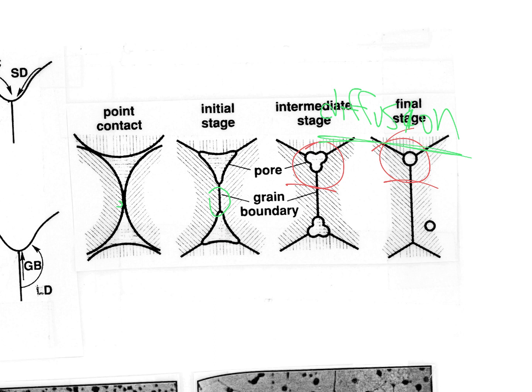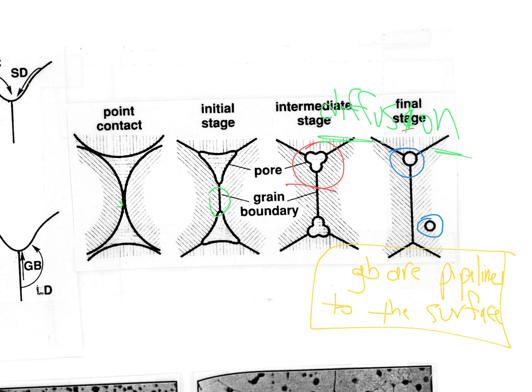All right, and a couple things can happen. Let me erase that part, and it shows you this here. We have pores in a couple of different places. This is a pore, and we've seen these before. It's on the inside of the grain. All right. And then we have a pore that's on the grain boundary. All right. And so the thing that I want you to keep in mind is the grain boundaries are pipelines to the surface. And I guess I could say diffusional pipelines to the surface.